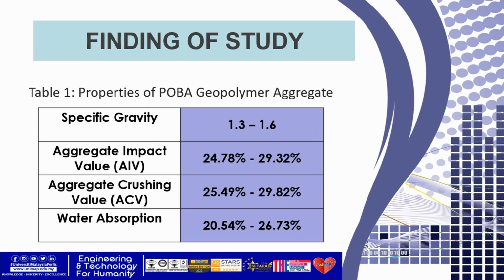For the findings of this study, as we can see in table 1, it shows the properties of POBA geopolymer aggregates. For the specific gravity, it has been obtained in the range of 1.3 to 1.6. And the aggregate impact value is in the range from 24 to 29%. The aggregate crushing value is in the range of 25 to 29%. And water absorption is in the range of 20 to 26%.